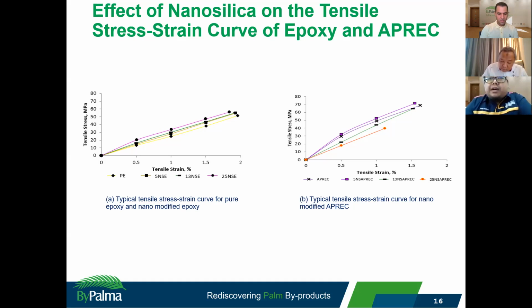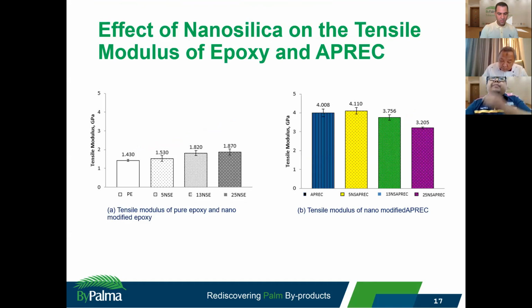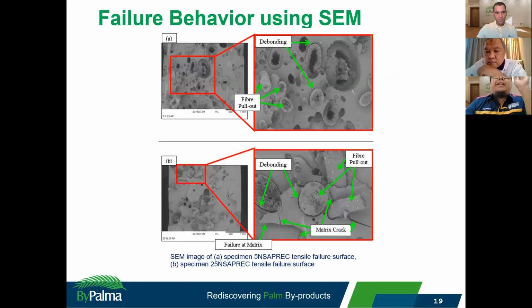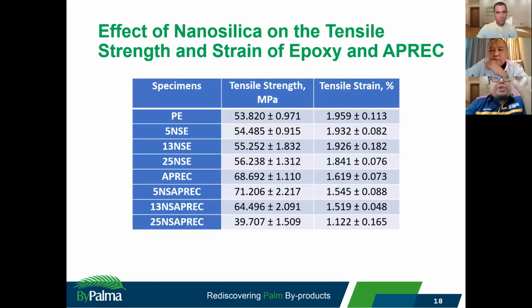For the modulus, it also shows the same. For the specimen without Arenga Pinnata, you can see the improvement on the epoxy itself, increasing from pure epoxy to 5, and then 13 and also 25. But when we use APREC, it only increases up to 5% nanosilica content. Why does this occur? We can see it in the scanning electron microscope later on. But before that, the tensile strength also gives the same result as the modulus: only up until 5% you can see the increment, and after we include 13 and 25, the strength is reduced.